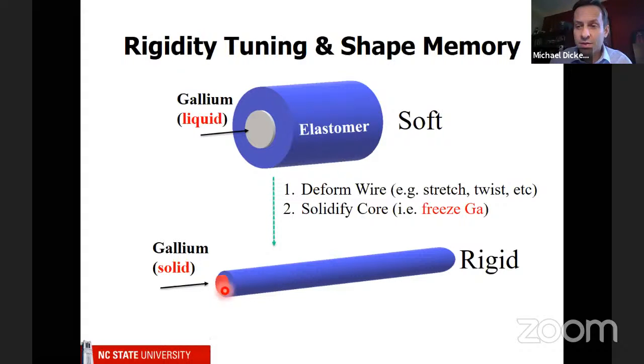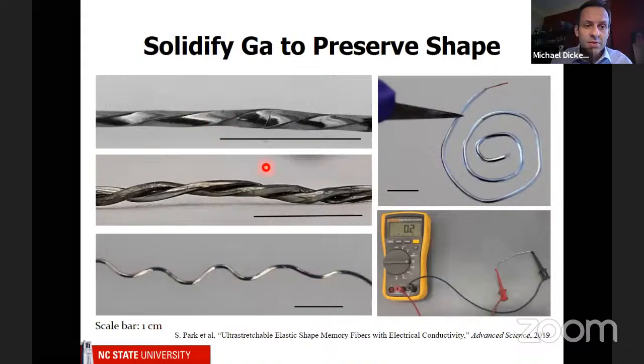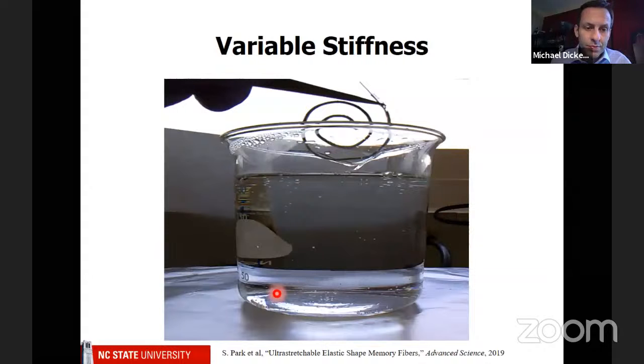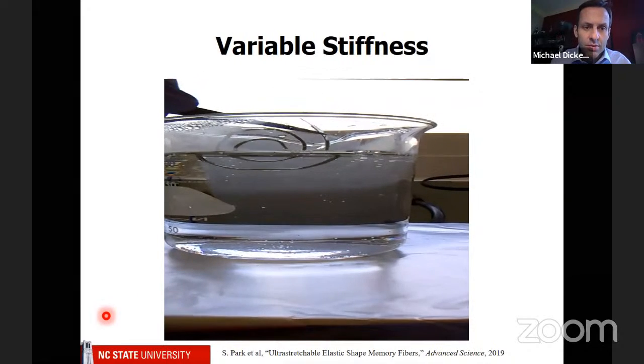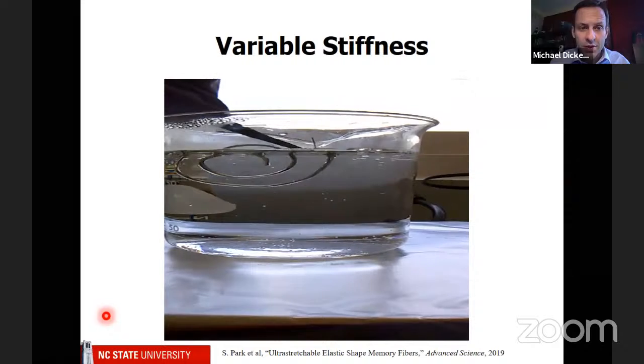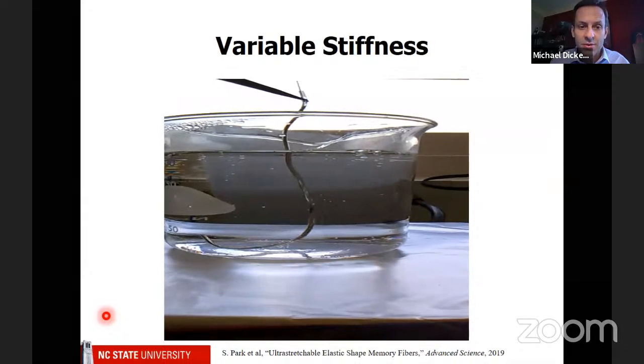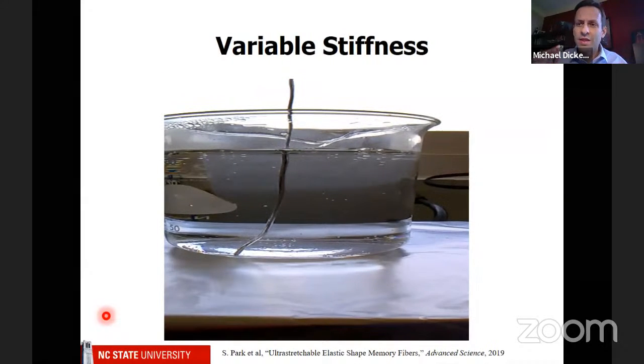And so this allows us to do some interesting things. So these are some fibers where we froze the gallium, and you can see it will keep its shape. So you can make it into whatever shape you want, but it's still metallically conductive. So you can see the resistance is very, very low. And when you put it into warm water, it will melt. And when it melts, it goes completely back to the soft state. So you can get, I think it's like 1,000 times change in the modulus just by controlling the temperature.